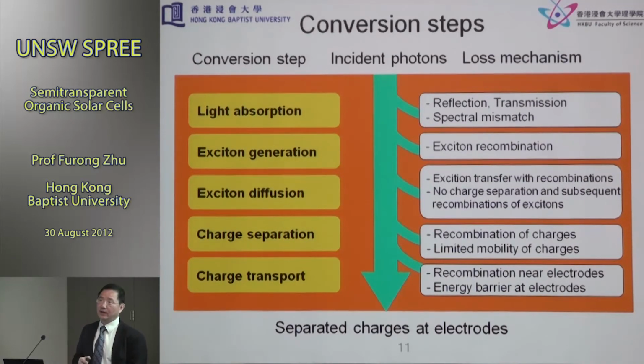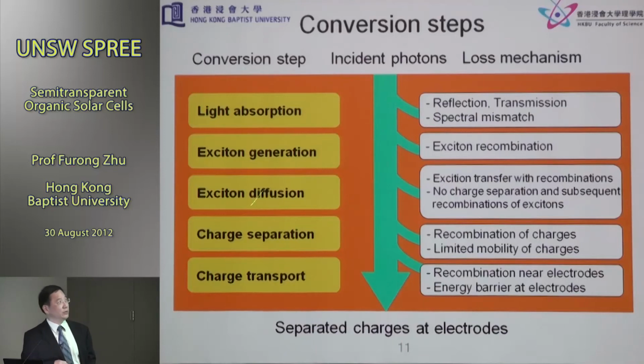They're called excitons. So these excitons need to diffuse and find a way to decompose, and usually they decompose at donor-acceptor interfaces, for example. But during the process of diffusion, they need to find a way to decompose effectively and become independent holes and electrons. They very often are lost to recombination, emit light, etc. So the efficiency can be low.